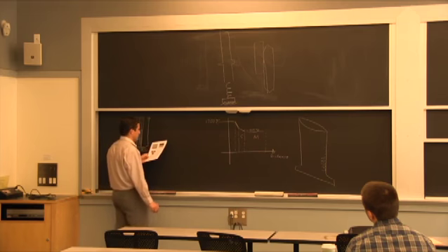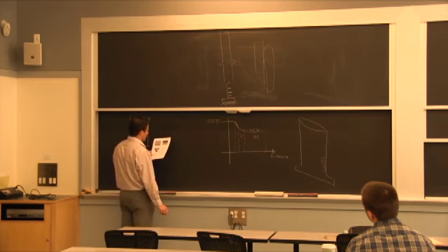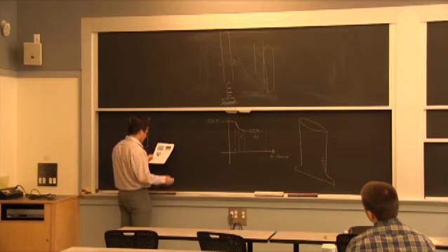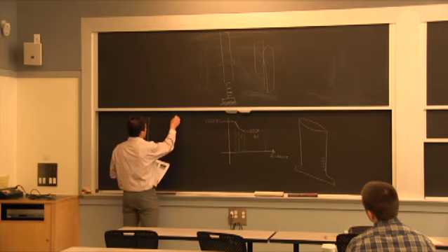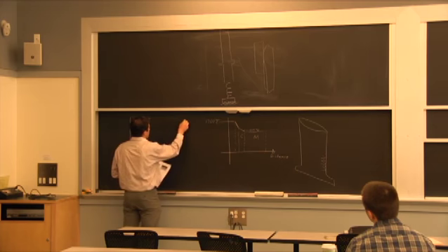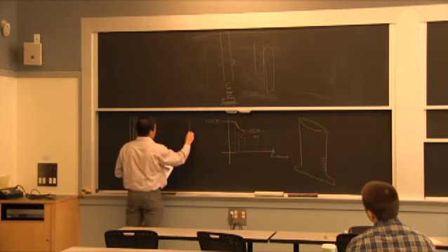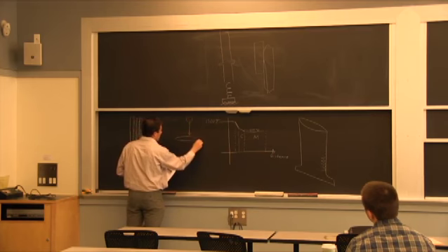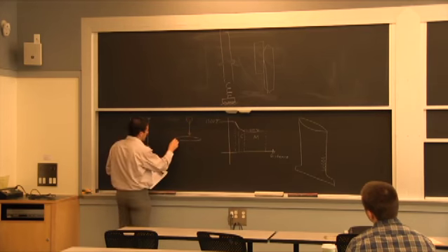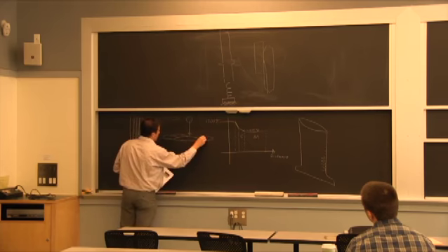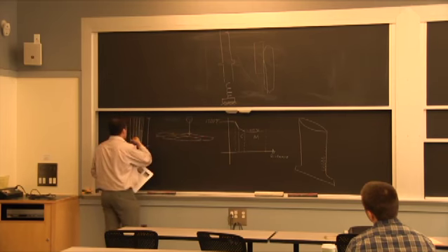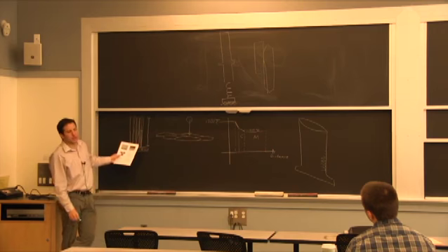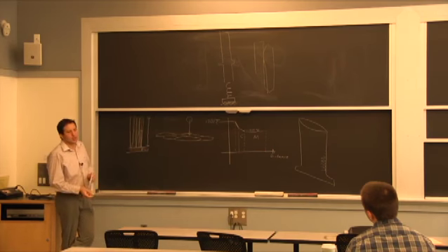So what I'm showing you on the right image is a thermal spray coating. The thermal spray coating is essentially droplets of molten ceramics. So they come down flat on the surface and they form these splotches. And you can form a bunch of them. They essentially stack in different ways. And your orientation is more or less the opposite of what we had by vapor deposition here.